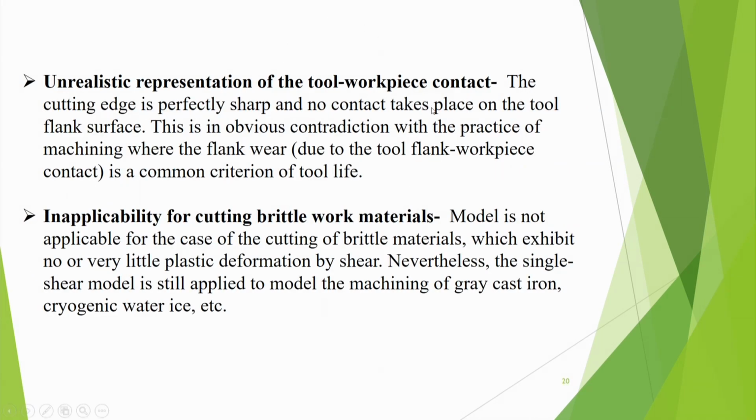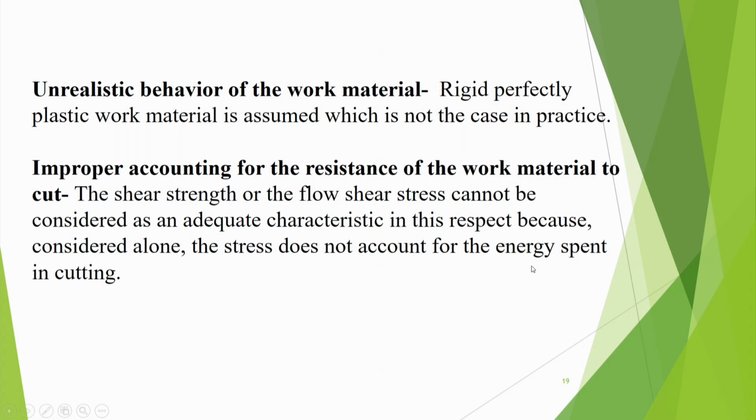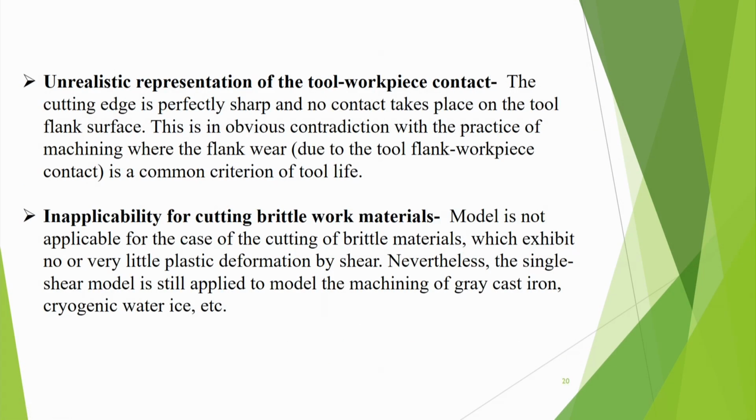Unrealistic representation of the tool work piece contact: the cutting edge is assumed perfectly sharp, and no contact takes place on the tool flank surface. This is in obvious contradiction with the practice of machining, where the flank wear due to the tool flank work piece contact is a common criterion of tool life. That means, there is some amount of flank wear on the flank surface, there will be contact. This surface is the flank surface, here some contact is there, but Merchant's model or single shear plane model is not taking that into account. And then, inapplicability for cutting brittle work materials.